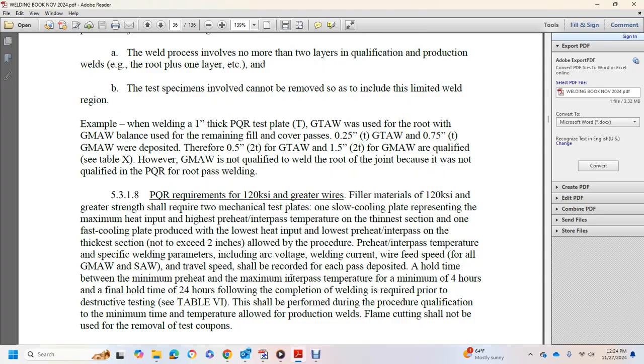Procedure qualification records for 120 KSI with a greater yield filler material with a 120 KSI tensile strength shall require two mechanical testing plates: a slow cooling plate represented with the maximum heat input with the highest preheat and interpass temperature for the thinnest section, and a faster cooling plate with the lowest heat input with the lower preheat and interpass temperature on the thickest section.